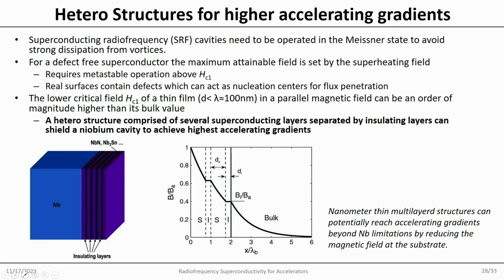So the idea is that I use several of these layers separated by small insulating layers, and each of them can remain in this flux-free state, thereby shielding the bulk. So it could be a niobium cavity with several layers on top of that. Each one remains flux-free, and the field on the surface would be much smaller than the applied field. By that, I can push to much higher accelerating gradients.